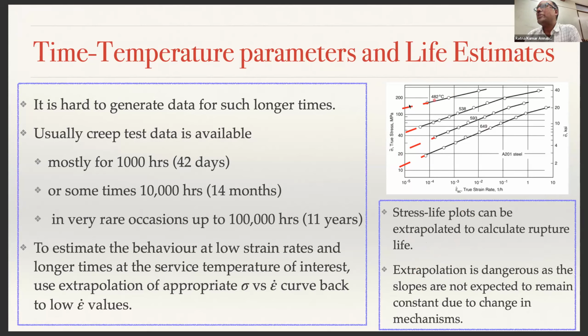Because the slope is not expected to remain constant. The slope may increase suddenly or reduce suddenly. If it is remaining constant, it's not a problem. If it suddenly increases, then the stress at which you think it is failing is not going to be that. Suppose, let us say, here it is like that and suddenly the slope reduces, then you will have trouble. And hence when you use creep data, there will be a lot of uncertainty, like fatigue data.